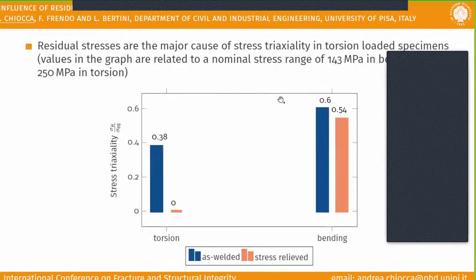So let's say that a factor that can describe this behavior at the moment is the stress triaxiality. We noticed that in the case of pure torsion, nominally the hydrostatic stress should be 0, and instead, when you introduce residual stresses, this hydrostatic stress changes. So it can have an influence on the final fatigue life of the specimens, while in the case of pure bending, the stress triaxiality factor was nearly the same for both as-welded and stress-relieved conditions.